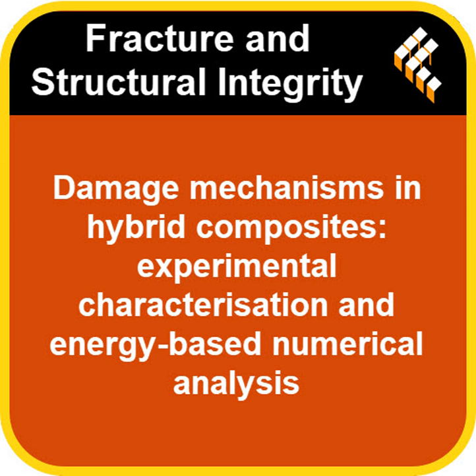And how did the hybrid materials perform compared to the ones that were just all carbon or all glass? Well, as you might expect, the hybrid composites generally performed somewhere in between the pure carbon and pure glass samples. No huge shock there. Right. And the exact performance really depended on what they call the hybridization rate, which is basically just how many layers of each type of fiber they used. More fiberglass layers generally meant the composite could bend further before breaking, greater displacement, but it couldn't handle as much overall force. Okay, so a trade-off.